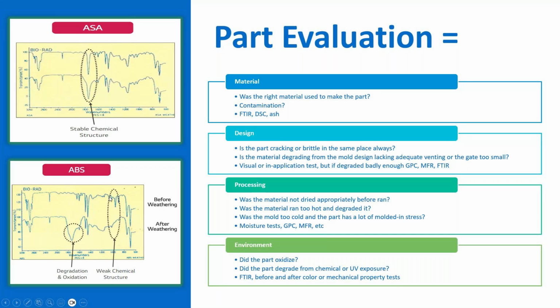And so these ones right here, as a little side note, is why we tend to say that if you can do it, ASA tends to be a better styrenic for outdoors. But a cool way for FTIR to show you the degradation that's occurring in ABS because of the UV weathering that it's being exposed to.